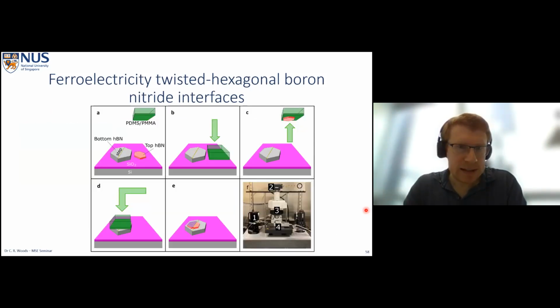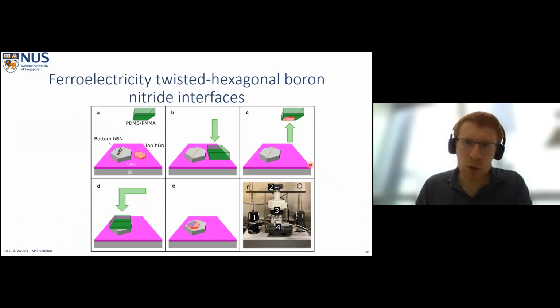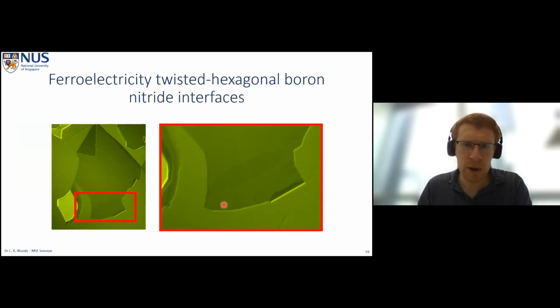We use a series of micro manipulation and polymer steps to lift up one boron nitride from a substrate, pull it across on our polymer, and put it down on top of the other boron nitride across the monolayer step using a transfer system, something like this. And when we do it, we end up with this. So this is our top boron nitride on top of our bottom boron nitride. This is just in case you're interested to know what these kind of things look like.